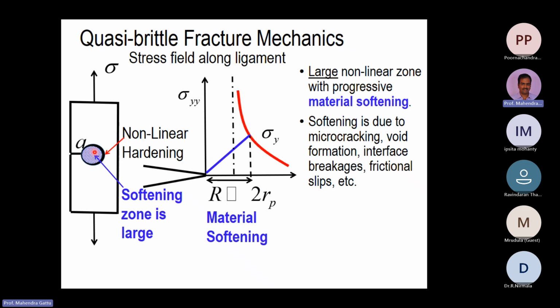This softening zone is very large, and it can be compared to the size of the structure itself. This is one of the key concepts in quasi-brittle fracture mechanics, the presence of a large softening zone. The zone of softening will exceed the plastic zone size for metals. The R value is very much higher compared to the plastic zone size in metals. This is the one key concept which I want you to take home from this presentation.